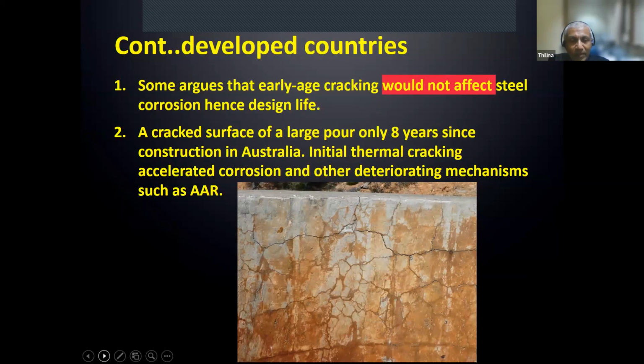The reason I put that is it sets in other deteriorative mechanisms as well, such as alkali aggregate reaction, where water will go through the cracks and accelerate it. This was initially cracked due to heat of hydration. After 8 years, it looks very ugly. So I just don't rely on those people who try to sell you snake oil saying don't worry about the crack width. If you write this spec, crack width 95 percentile should be less than 0.2. That's what it should be.